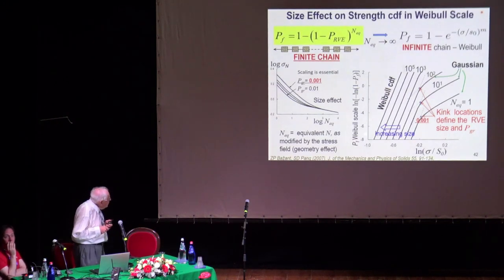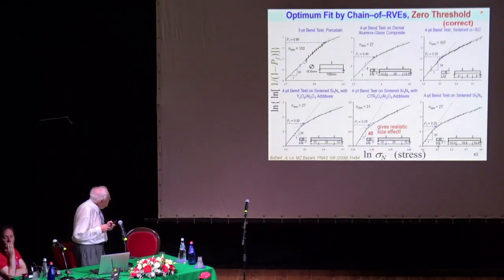So what I'm plotting here is a Weibull scale. In the Weibull scale, the Weibull distribution is a straight line, given by this formula. If you plot it in normal probability paper, of course, it's a curve. It's a straight line for a small element, up to a probability of 1 minus 10^-3, then a deviation. As the size increases, it goes up by orders of magnitude, and this point can be determined from the size effect, because depending on this transition you get different size effect curves, which can be measured and have been measured. So that's a brief summary of a long theory, but it's validated by experiments.